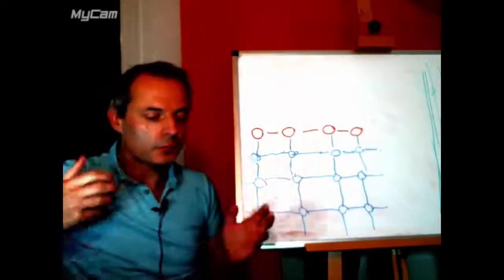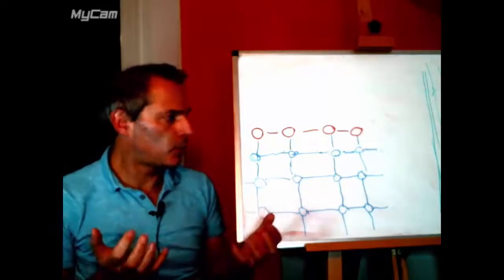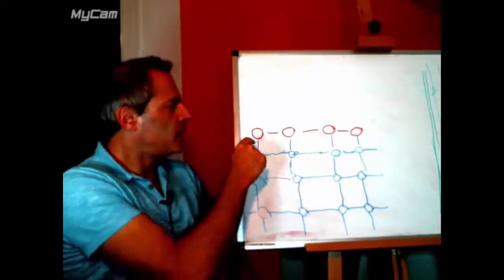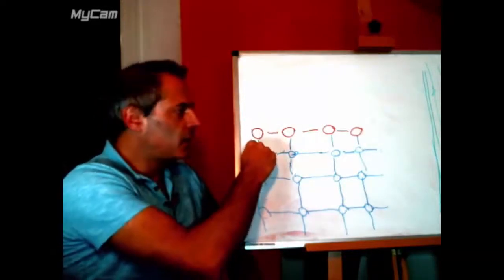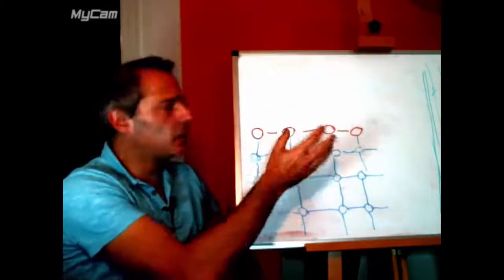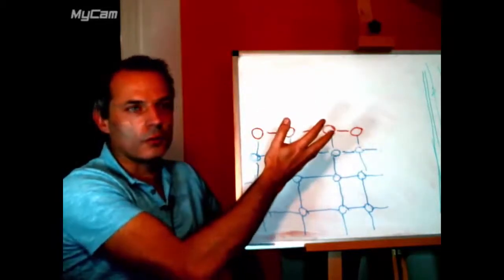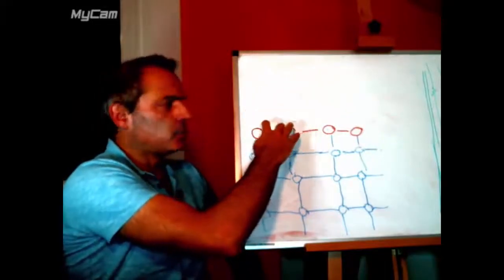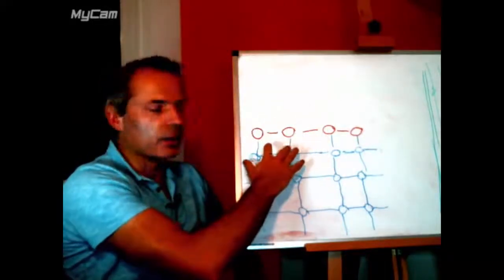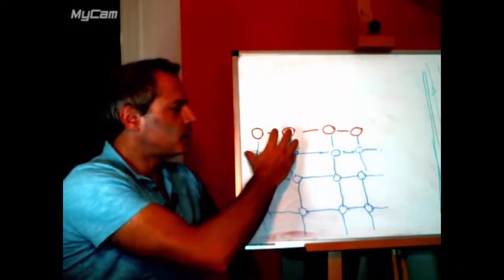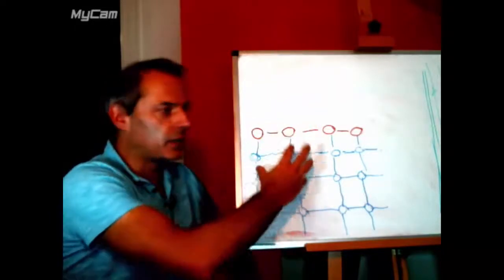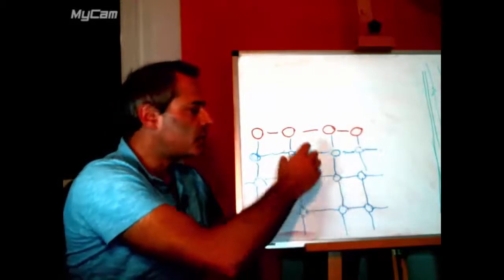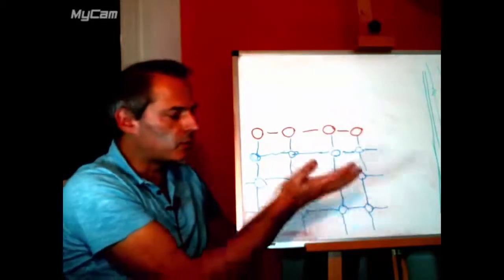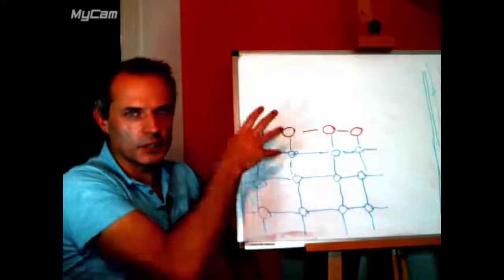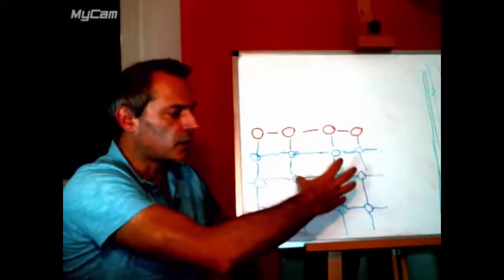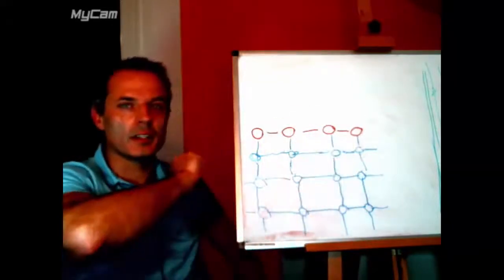And if we think of it as a Gibbs free energy question, the global Gibbs free energy is not only this bonding energy here, and not only the loss of entropy because we've added some atoms that were free and now they're not free, but it's also the gain in energy from the strain, from leaving the strain in all of the other bonds down to maybe 5 layers down from the surface, obviously getting less and less as we go down because the strain is less and less, it's worse at the surface.